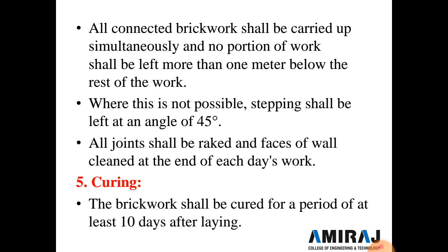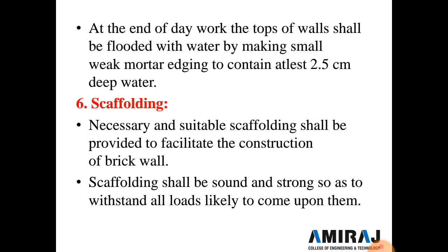The next specification for first class brickwork is curing. The brickwork shall be cured for a period of at least 10 days after laying. Here compulsory sprinkling of water is required for brickwork, and at the end of the day's work, the tops of walls shall be flooded with water by making small weak mortar bunds to contain at least 2.5 centimeter deep water. The sixth important point is scaffolding.